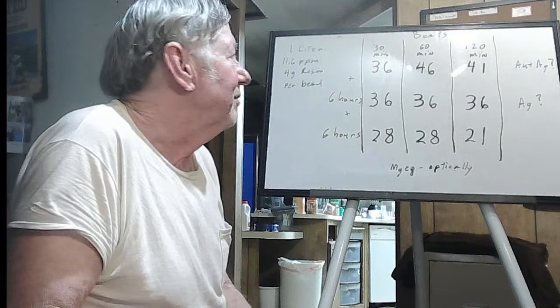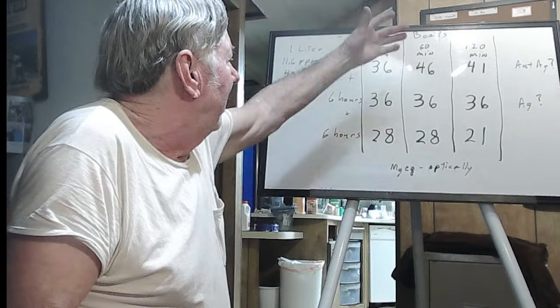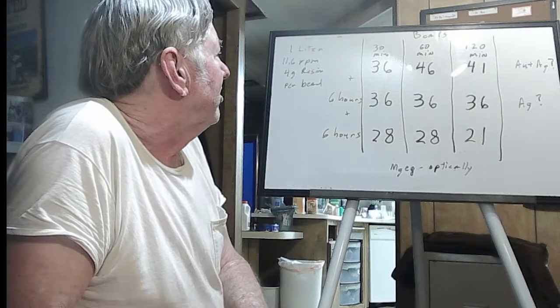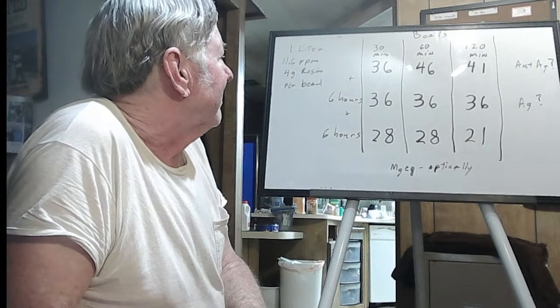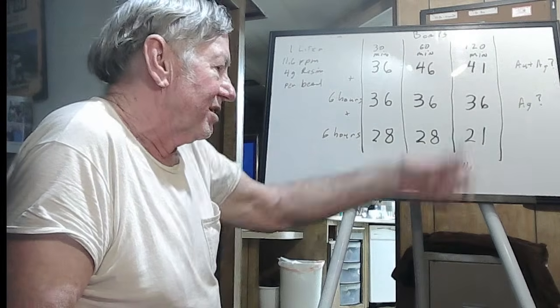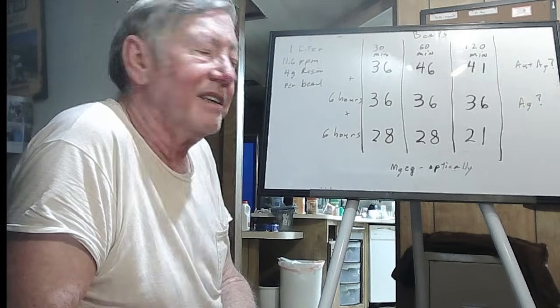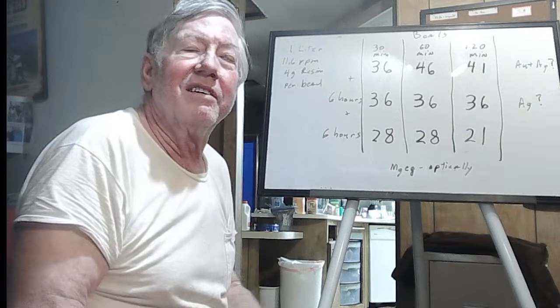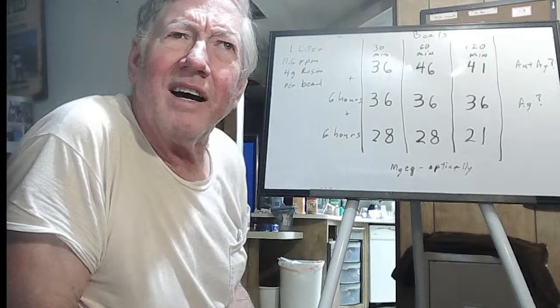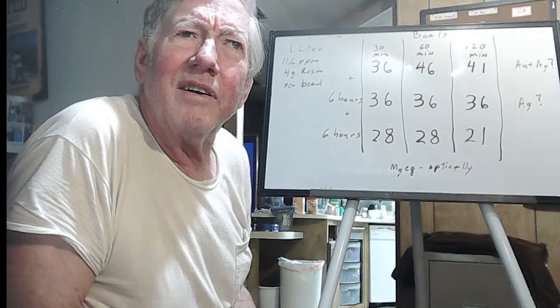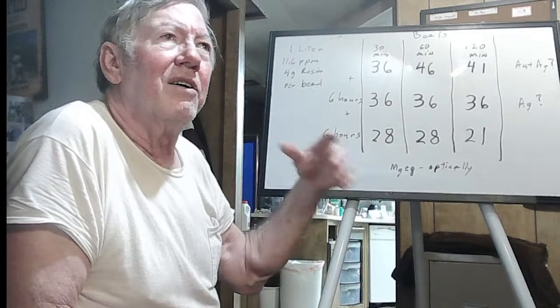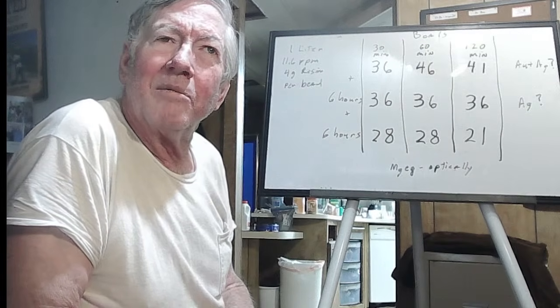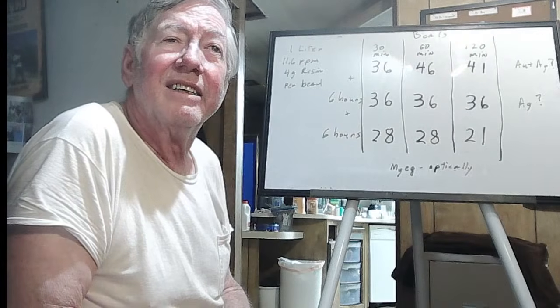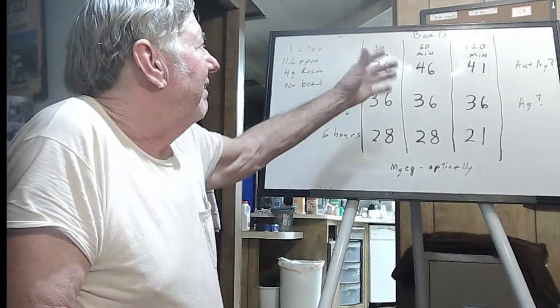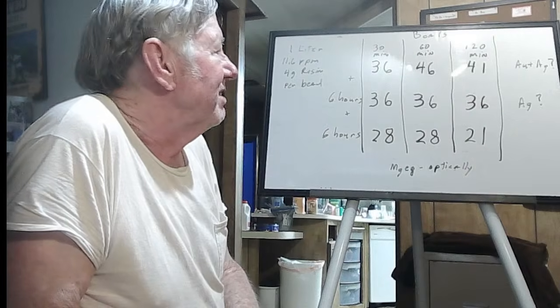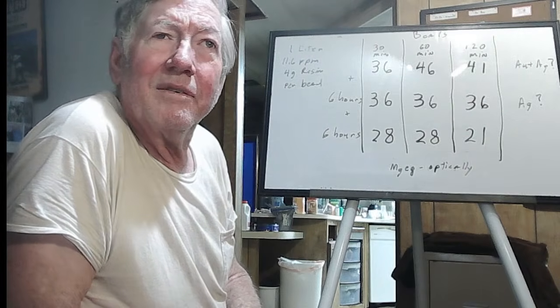How can we do it? For example, if we were to take the slurry and let it settle for a couple of hours, like you just turn off the cement mixer and let it sit for a little bit, and then pour the fairly clear liquid off the top, you could run that through a resin column or something like that fairly easily. And then maybe a resin and pulp for the rest of the mud, so to speak.